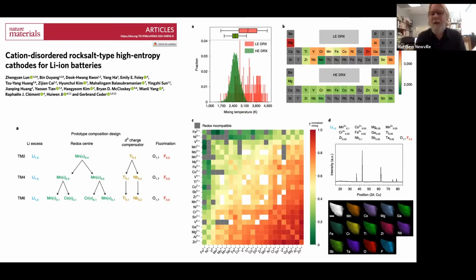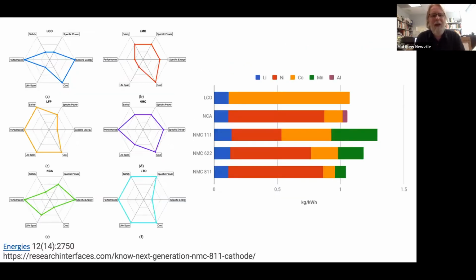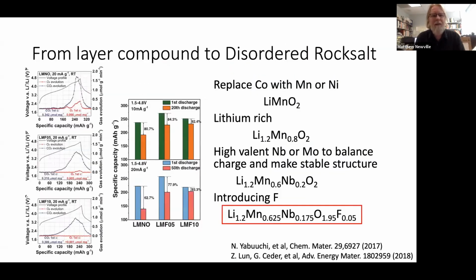You're welcome. So I don't see any other questions, but I have one. In these transition metal oxides where you are overloading them with lithium, when you get to lithium 1.2 and a mixture of transition metals, how much of that lithium is actually active, and can move out and participate in the charging? It depends on your system. For the lithium cobalt oxide, we know only half of the lithium can be pumped out in theory. And so that's why we are trying to mix as much lithium as possible usually. Right.